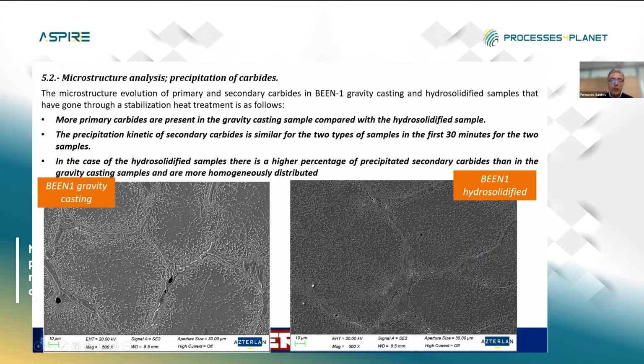what we have done is to make a stabilization heat treatment, because we have seen that the condition of the alloy changes with time. If we keep it at 930 degrees for some time, there is a significant precipitation of carbides. So we have carried out this stabilization heat treatment.